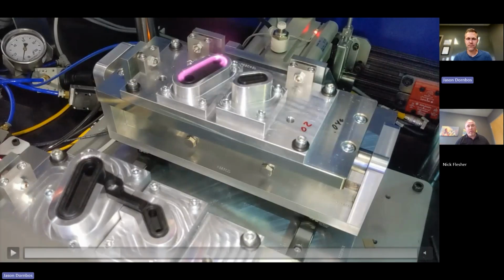We have a customer that has a gray part, and 2 micron gives them just the right heat affected zone, just the right amount of energy. And that was what they wanted. 1 micron was actually too surface oriented. So 2 micron actually soaks in a little bit more. Not all the energy is absorbed at the surface, whereas 1 micron is very, very surface absorptive.